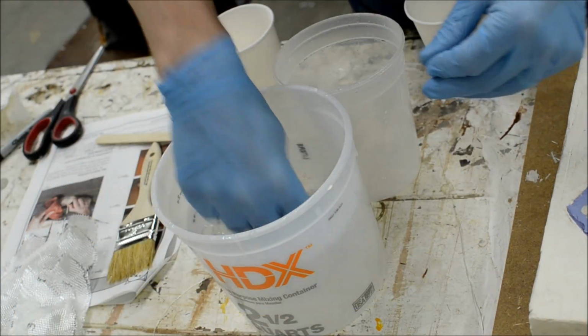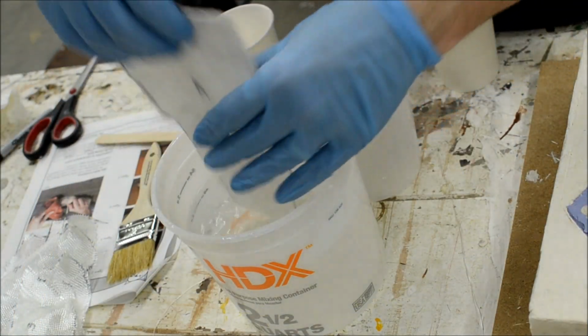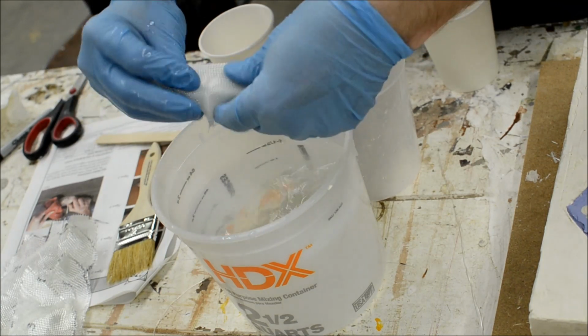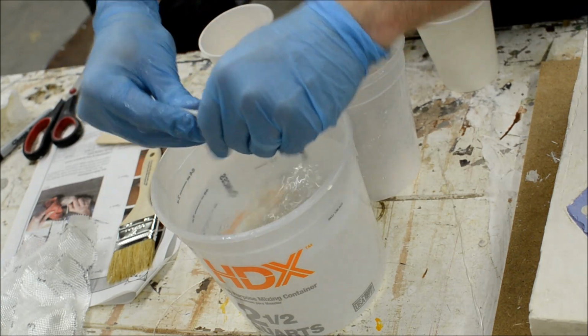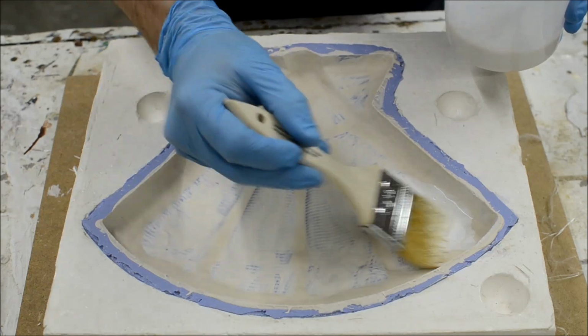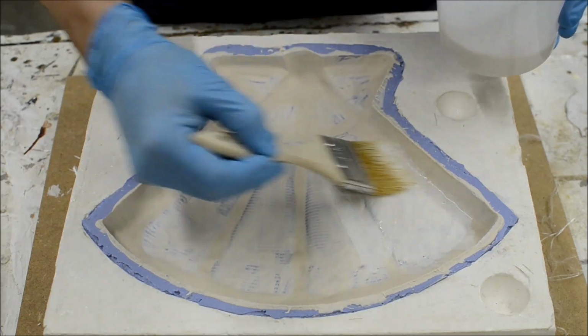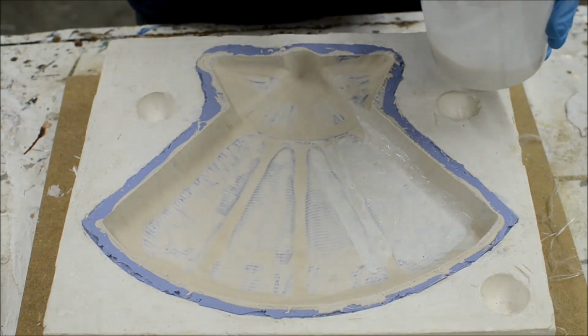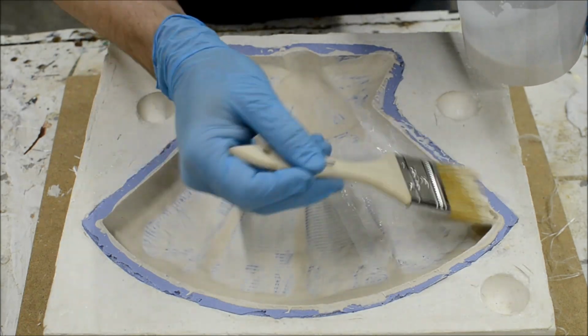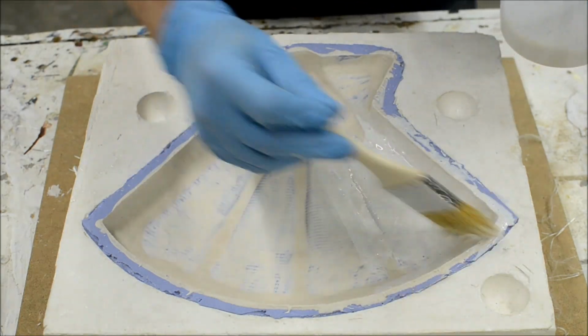Soak the fiberglass in water and wring it out fully before applying it. This will help the resin absorb into the entire cloth. As soon as the surface coat is dry, in about 10 to 20 minutes, you can apply the fiberglass. Paint another coating of resin over the mold right before laying in your cloth.